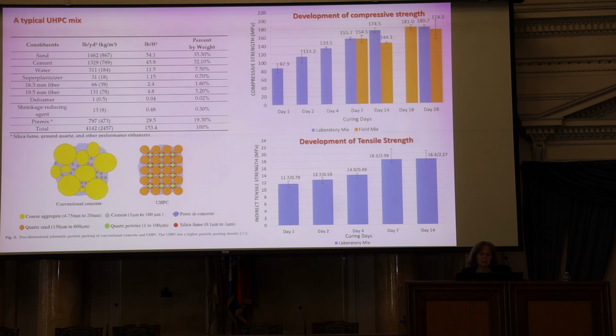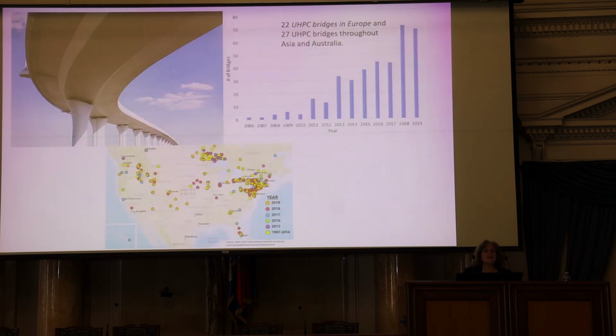How does it perform? Well, the top graph shows you the evolution of the compressive strength of this material. If you look closely, the blue line is the laboratory value, and the orange column represents the field value. We are talking about strengths in the range of 180 megapascals in compression. These are huge strengths. The most interesting aspect, though, is the tensile strength. So you see the evolution in time with curing of these materials in tension. You see that we have strengths in tension of the order of 11 megapascals or more. So suddenly, this has opened up huge opportunities, particularly in bridge engineering.